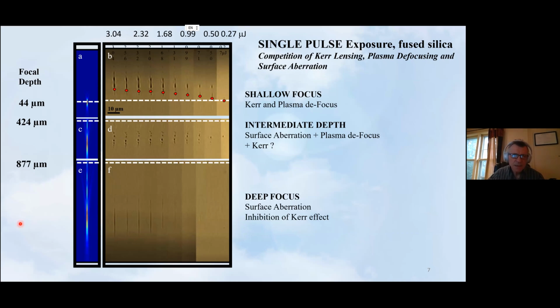So here is focal depth, 44 microns, so near the surface, but almost a half a millimeter deep and almost a millimeter deep. And the surface aberration that I mentioned is an imperfection in Snell's law. And this is close in shallow focusing to what a Gaussian beam looks like. You can see the beam profile, a narrow width and a depth of focus. But as you go deeper, you get the surface aberration. There's the intended paraxial focus, and the beam stretches below.